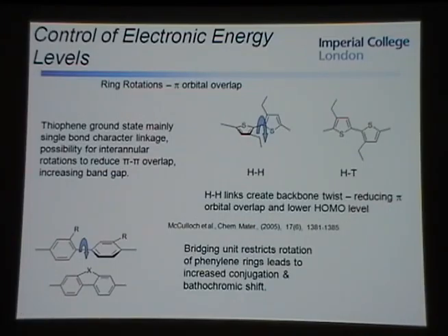But yeah, the chemistry of how you make these is quite important, and that applies to all polymers actually. You can make the same polymer by 3 or 4 different synthetic routes and get a completely different performance depending on the defects. And that's not always talked about or appreciated maybe. Usually that's not particularly desirable because that will affect the ability of the polymer to crystallize. It will affect the band gap, which perhaps you want, but if the polymer is amorphous, you're going to have a very low charge carrier mobility, so that's not necessarily good.